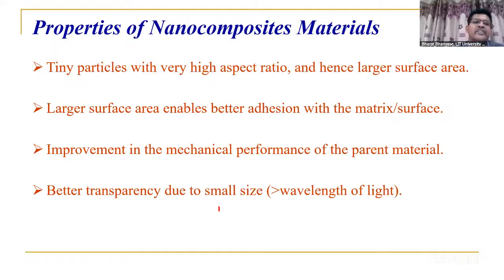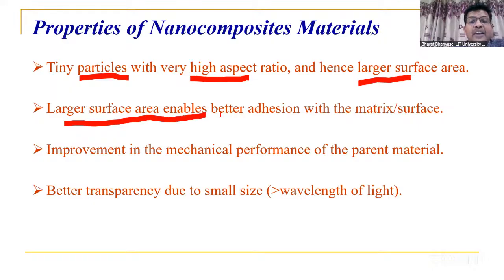Okay. So, properties of nanocomposite material. That depends on particle size. Then what is the aspect ratio? That means it is a rod shape or platelet-like structure. Therefore, it depends on the high surface area, so that is very important. Large surface area you will observe in the case of nanoparticles. Then larger surface area enables better adhesion with the matrix. So that is again very important.